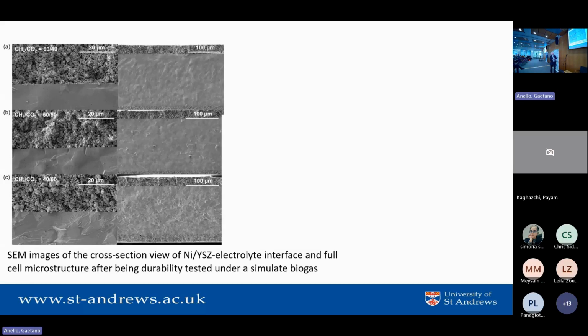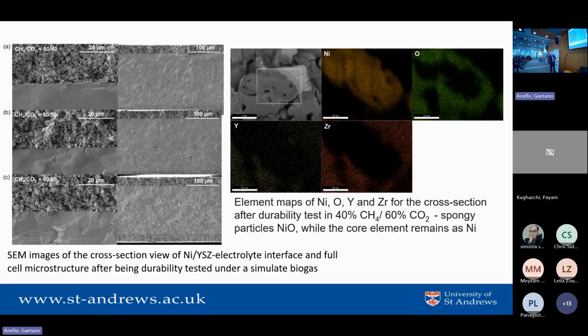And then looking at the structures after electrolysis, if you look in more detail, you can see why the degradation is coming. We didn't see any carbon, but we see oxygen where there shouldn't be oxygen. So you end up with a very spongy nickel oxide on top of the nickel. So the nickel is restructuring in response to the gases.